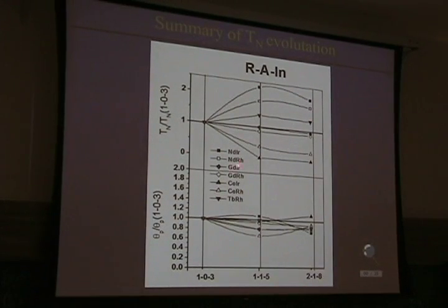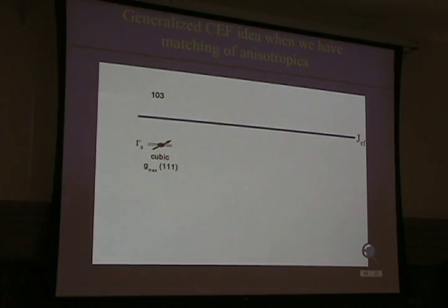Well, you see that terbium, like neodymium, has a larger T-Néel for the tetragonal compounds when you compare to the cubic ones. So here you get gadolinium, here's the cerium. Cerium so far is the only one whose T-Néel decreases when you go from cubic to tetragonal. Neodymium and terbium both have increases in the Néel temperature. So there's a difference between terbium and neodymium, and cerium.